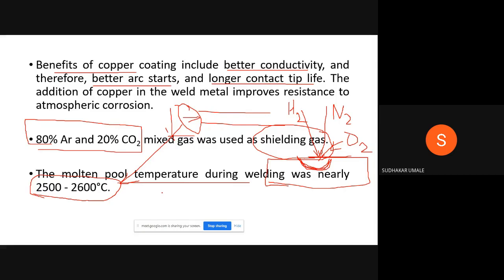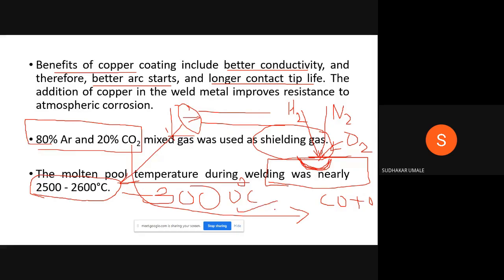Now, what is the disadvantage during this process? If by chance we get a maximum temperature of more than 3000 degrees centigrade, now what is the dissociation? This CO2 will absorb the heat from the arc and dissociate into carbon monoxide and oxygen. You take care of it. If you cannot confirm that the welding temperature will not rise beyond 2000-3000 degrees centigrade, don't select CO2 as a shielding gas. Otherwise, this shielding gas creates problems in the weld metal.